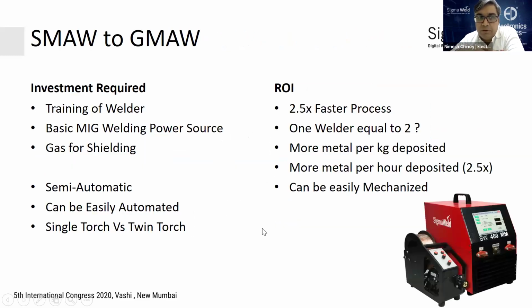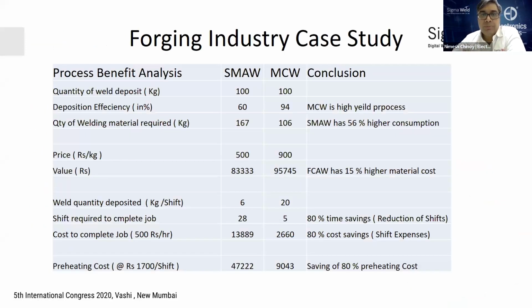That means less amount of material, more amount of throughput, right? So you can increase your ROI by 2.5 times, because the process is that much faster. And you can have more metal per kg deposited, more metal per hour deposited, and the process can be easily mechanized. This is what an arc welding or a flux core MIG welding machine looks like. You can go for single or twin wire both.